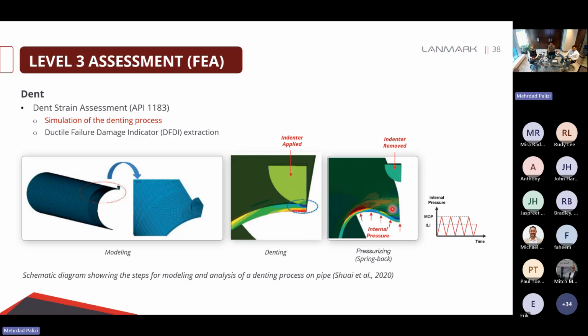So what is the challenge here? The challenge is that by the time we are finished with our modeling, we should do a comparison between our simulation and the ILI data. If our simulation is not matched reasonably over the ILI data, then we're going to have to go back to this step. We're going to change the dimensions, the shape, and the movement of the indenter, and repeat this process until we get a reasonable match.